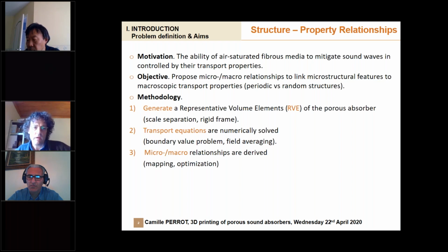And then, if you want, and this is generally what is done when you are dealing with an industrial problem, you establish relationships from microstructure to macroscopic properties in order to get a kind of mapping between local geometry parameters and transport parameters, which gives you the sound absorbing behavior. From this mapping, you get a kind of surrogate model, which is suitable for optimization purposes.